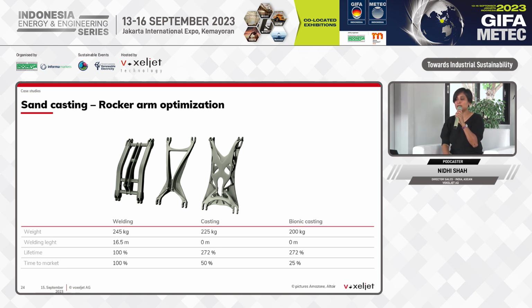Another application for rocker arm optimization. This is for the Amazon equipment, and as you can see, earlier the component was being manufactured by welding, then the customer moved it to casting, but with the help of 3D printing they were able to change the design completely to bionic casting. The weight was reduced from 245 kgs to 200 kgs, the lifetime of the part was increased by over 150%, and the time to market was just 25%.